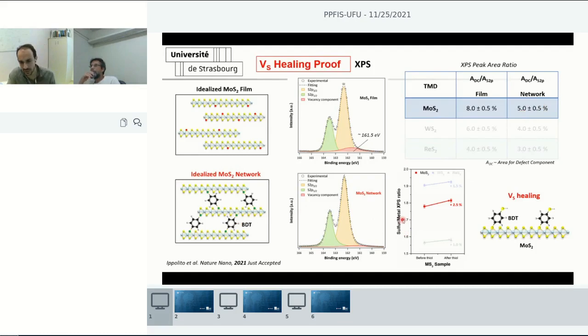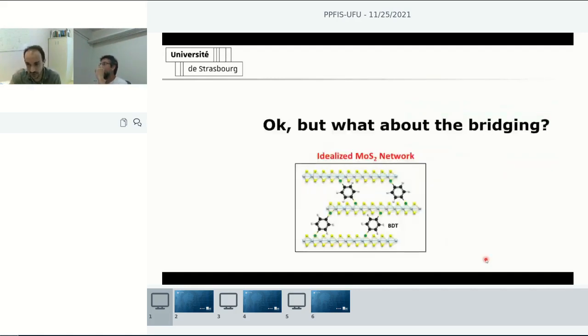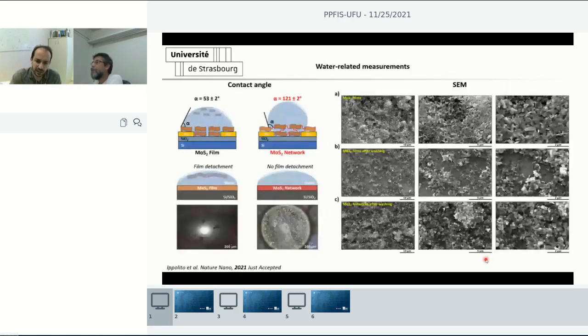If we also do the ratio between sulfur and metal from the XPS data, we see that there is a slight increase of the ratio between the signal from the two atoms. So from this data here, we can claim there is healing, so substitution, the attachment of the molecules to the sulfur vacancies. But what about the bridging that I talked about?